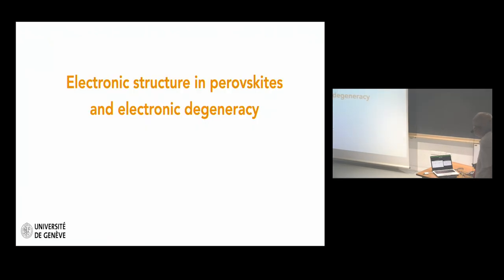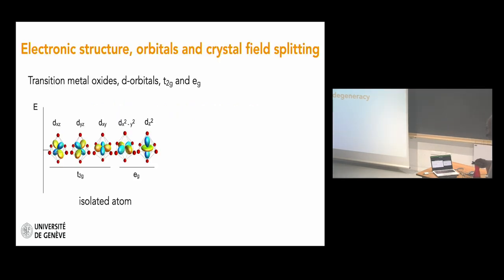Okay, let me now discuss the electronic structure in perovskite, and the electronic degeneracy. Now, one thing which is important, and probably that maybe everyone knows, is that we are in transition metal oxide, so we deal with d orbitals, t2g and eg orbitals. Now, if you have an isolated atom, so forget now about the oxygen octahedra, these orbitals are degenerate. But now in our perovskite structure, we have the oxygen octahedra.